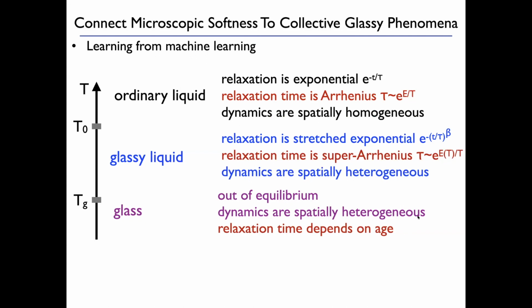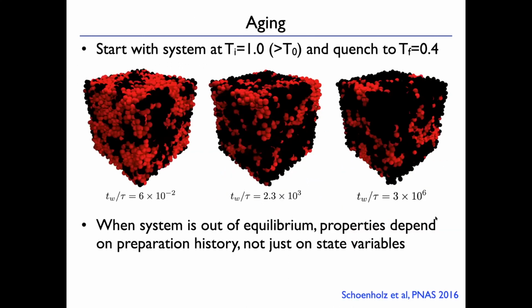Okay, let's go on to the next thing, which is this thing about the relaxation time. Can we understand that behavior of the relaxation time, whether it's Arrhenius or super Arrhenius or what? To do this, we're going to look at aging. So we're going to take the system, we're going to quench the temperature from above the glass transition to below, okay? And now, when we're below it, we can't wait long enough to equilibrate. But the system does evolve with time.